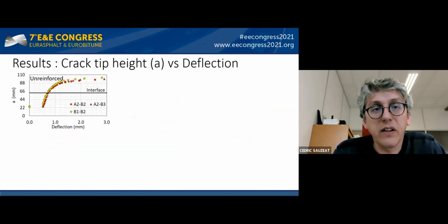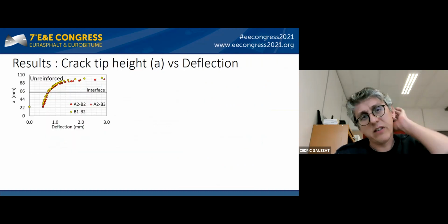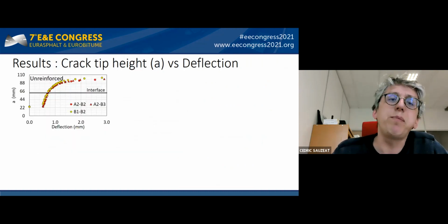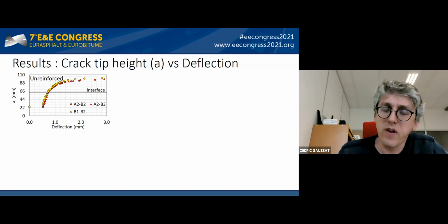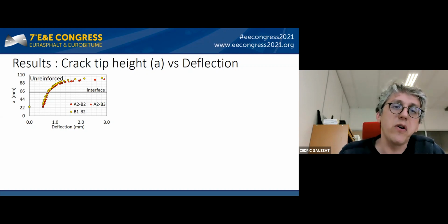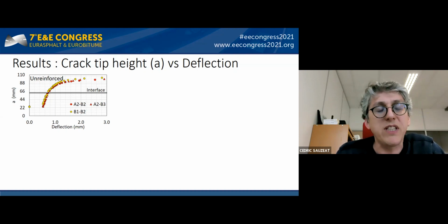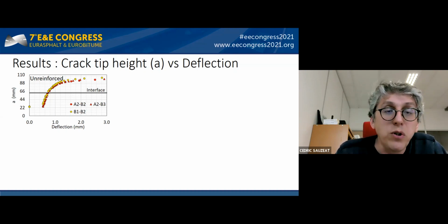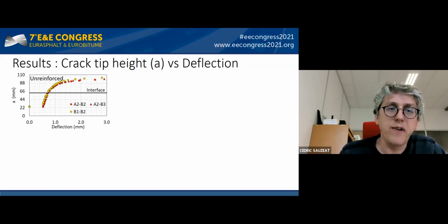We can see the second results. So the evolution of the crack tip in function of the deflection. So you have here the classical evolution of the crack tip for the two unreinforced specimens. You don't see any real difference.